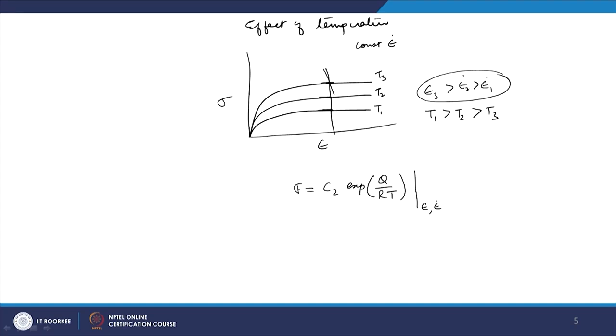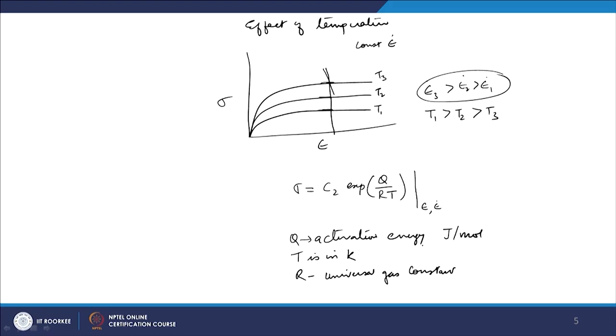So, as temperature increases, my stress decreases. This Q is the activation energy for deformation, and its unit is joule per mole. Temperature is of course in Kelvin, and R is the universal gas constant. C2 is again some constant for the material. Again I can find out the value of Q here. If I take logarithm on both sides, it becomes ln sigma equals ln C2 plus Q by RT.